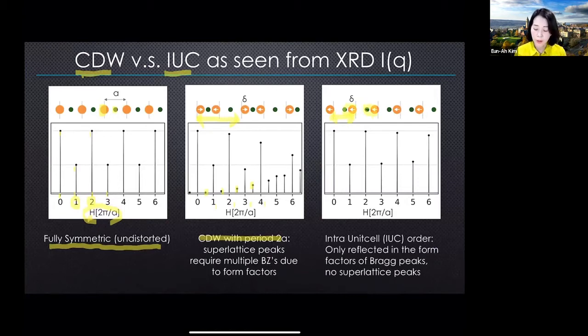This symmetry breaking would manifest itself in X-ray data only through the form factors of Bragg peaks, meaning we have peaks at the same integer positions. We do not have any new peaks, but you can observe that the heights of these peaks are changing subtly compared to the undistorted case. And you can imagine that this intra-unit cell order, without a new peak showing up, could be much more tricky to detect.